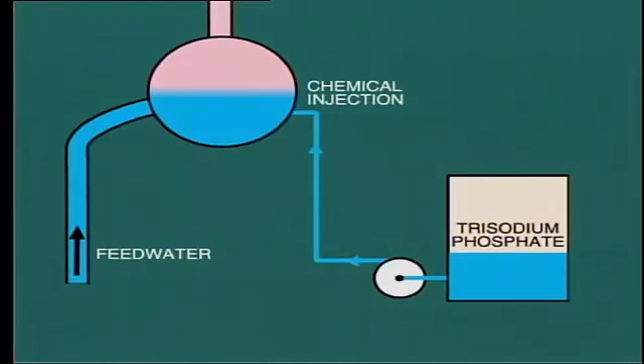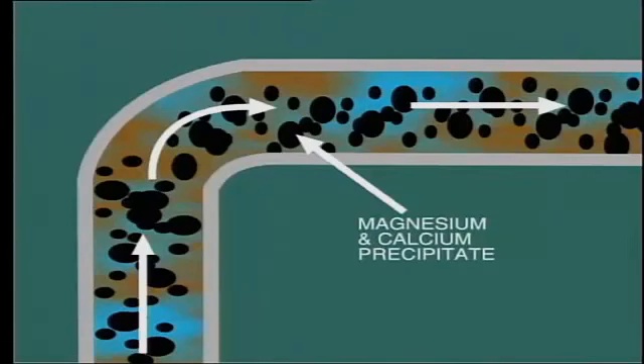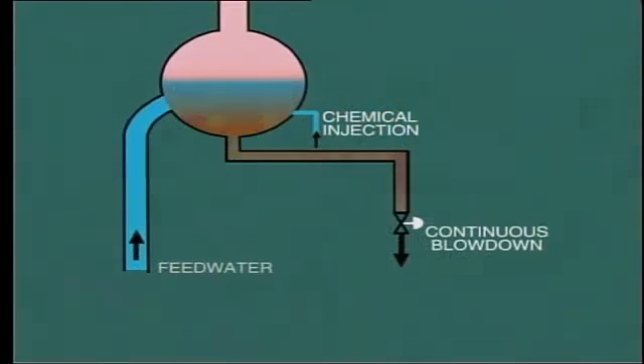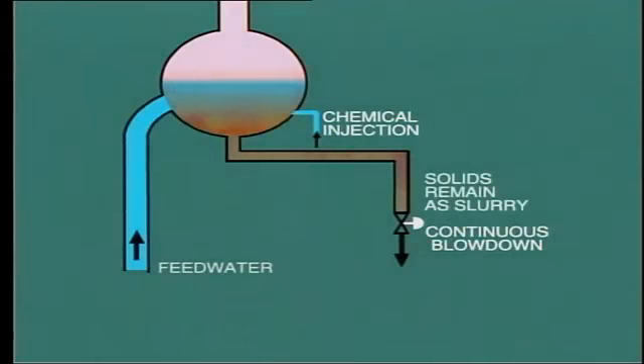Even with all of these precautions and controls, there is still a tendency for the concentration of solids to build up in the boiler water. For this reason, an attempt is made to prevent scale formation by injecting a chemical dispersant such as phosphate into the boiler water. This is usually added at the boiler drum, so a high-pressure pump is required. Phosphate has the effect of keeping the magnesium and calcium precipitate in suspension by dispersing the solid particles throughout the water. The result, then, is that instead of forming a hard scale, the solids remain as a slurry to be discharged from the boiler through the continuous blowdown line.